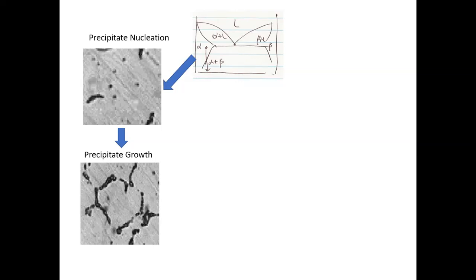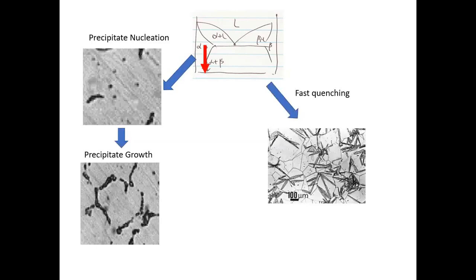However, as you can probably imagine, now if I do not do this very slow cooling, where I give the atoms sufficient time to diffuse around and grow into the beta phase, and I do this very quickly, typically we call this quenching, which means a very quick drop of temperature of the system. What do you think is going to occur in those cases? If we do not give the atoms sufficient time to diffuse around, what do you think is going to happen? The crystal structure that's present at whatever temperature you had will freeze. Basically, the B atoms are randomly distributed in the A atoms of the solution, right? But if you do not give them sufficient time to diffuse around to form a second phase, you just freeze everything in the original position, right? So this is very intuitive. And indeed, this is what you're going to see in most cases: the solutes freeze where they are in the system.